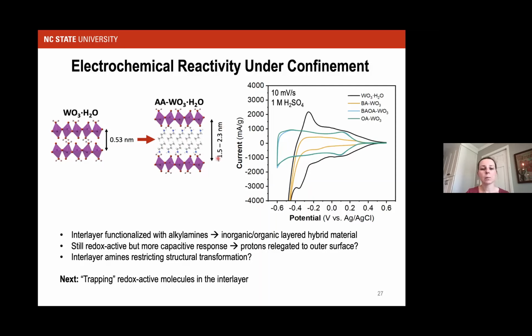And so the next step for this work is to start trapping redox active molecules within the interlayer and see whether they can undergo charge transfer that way. And there is work from folks like Graham Newton's group, where they looked at polyoxometalate clusters confined in carbon nanotubes that show that this can be possible, and there's some very interesting phenomena at work.